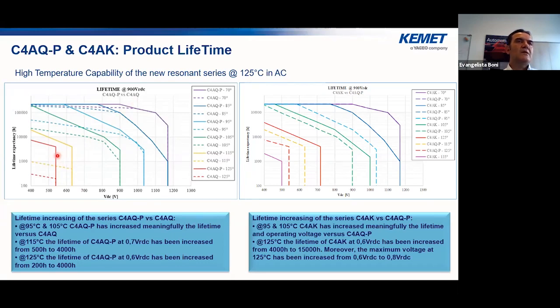For instance, we can make some comparison at 125 degrees where we can see that C4AQP moved from the 200 hours of C4AQ to 4,000 hours of C4AQP at 0.6 rated voltage. On the right, we can see the similar graph, but making a comparison of the C4AK versus the C4AQP. And then we can see that at lower temperature, the lifetime is the same. So at 70 degrees and 85 degrees, the lifetime is the same. But at higher temperature, the lifetime of C4AK is much higher.